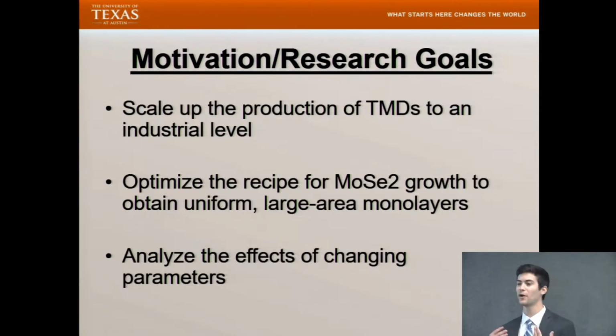So the primary motivation of my research is that TMDs are most often acquired using mechanical exfoliation, which is basically just tearing away layer by layer of the bulk material using tape until you acquire a monolayer. And this process is just far too inefficient and time-consuming for commercialization. But chemical vapor deposition, on the other hand, is able to produce large quantities of TMDs at a much faster rate. So the method that I'm researching holds great promise for future industrial production.